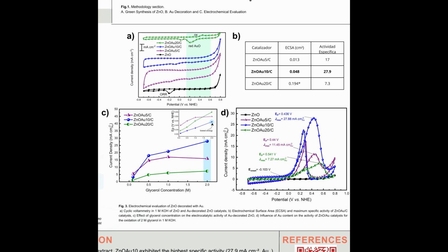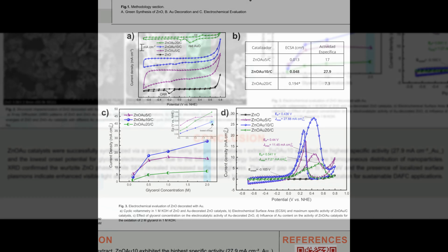Mechanistic interpretation. The proposed bifunctional mechanism involves zinc oxide absorbing hydroxide ions from the alkaline electrolyte and transferring them to nearby gold sites where glycerol oxidation proceeds more efficiently. The optimal balance of gold dispersion and zinc oxide gold interface in the 10 millimolar sample explains its superior performance.